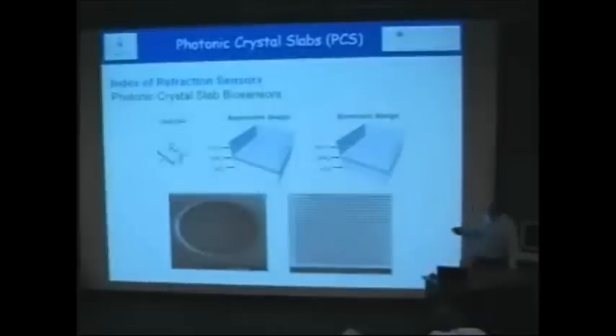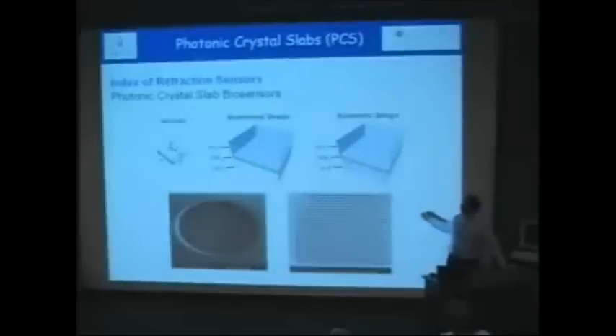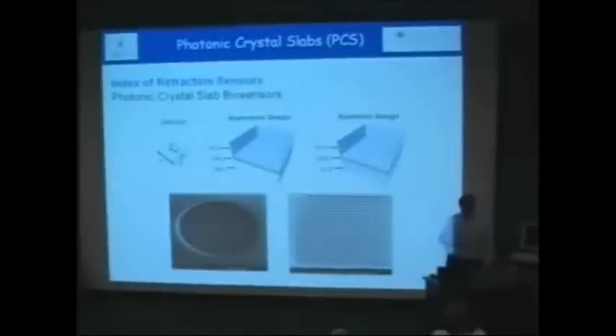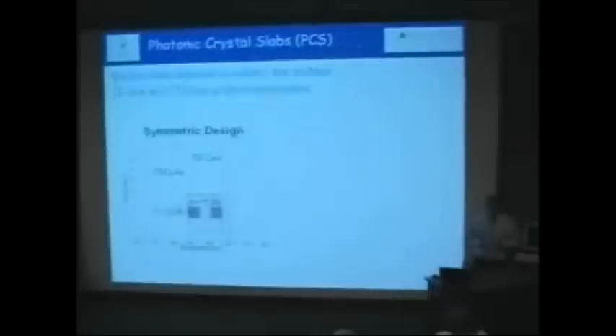And we tried to look for designs that have a symmetric design where we have water both above and below the structure, so we create guided resonance within the structure. We like to use silicon nitride because it's transparent in the visible and transparent in the near infrared, and it's very flexible to work with. And we looked at a design that is all transparent with the silicon dioxide or quartz underneath as the substrate, versus a case where we totally removed it and saw that we could get a symmetric design.